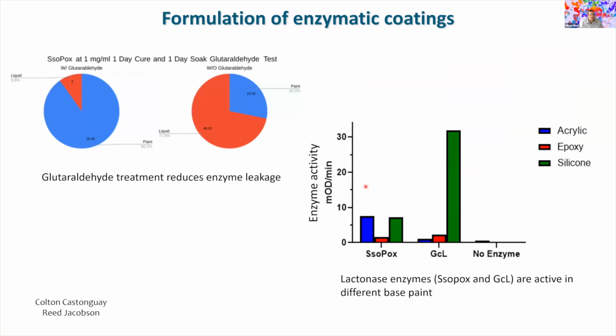So from there, with the help of MyCirc, we did a significant amount of work in trying to formulate better coatings. Those are just small examples, and I apologize for the quality of these figures. Somehow they come up blurry here. But we identified ways to reduce leakage. So for example, here, without glutaraldehyde, so glutaraldehyde is a chemical that will covalently immobilize, at least we hope, the enzyme onto the polymer. We see without glutaraldehyde, a lot of the enzyme activity is leaking into the liquid phase, and about 28% of the activity is in the paint. And with glutaraldehyde, more than 90% of the activity remains in the paint, and only about 10% is leaking into the liquid phase. So this is really reducing that leaking issue.